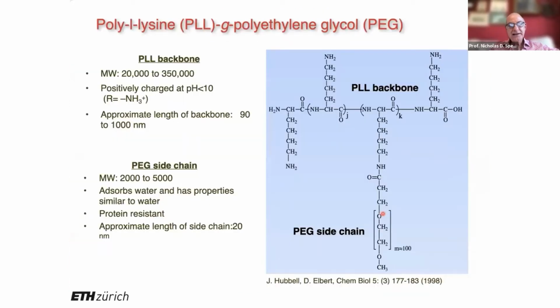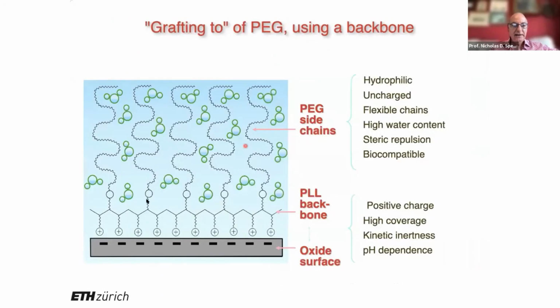So where we started in this game was using this molecule called polylysine grafted polyethylene glycol, or PLL-PEG, and it's a lot less frightening than it may look at first. It's just a whole bunch of amino acids hooked end to end, all the same amino acid. It's lysine here, and lysine has this characteristic of an NH2 group. In water, that will pick up a positive charge, but we can also use it for functionalization. So on some of them, we hook on this long PEG chain, some of them we just leave so that they retain their positive charge. And in the end, it looks something like this. We have the backbone, we have the positive charges, and then we have the PEG chains.